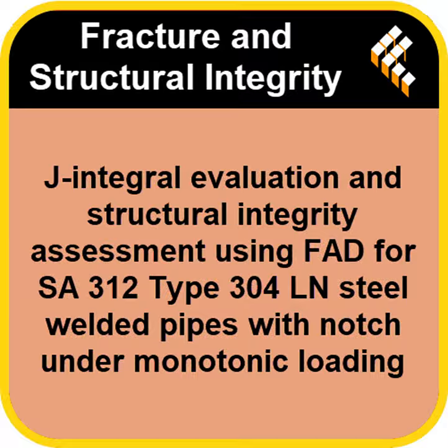But I'm guessing the material properties were a different story. That's where the sensitivity showed up, yes. It confirms that it's often the quality control and precise knowledge of the metal itself that dictates the real margins. Makes sense. Indeed. They saw significant percentage variations in the LR and KR ratios, linked directly to the inherent variability or measurement uncertainty in those material properties. For instance, flow stress variability, that capacity to strain harden we talked about, caused a maximum variation in the load ratio, LR, of up to 7%. 7% change in LR just from a plausible uncertainty in flow stress.